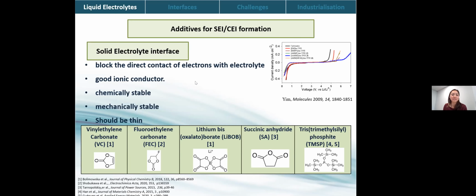It has to block the direct contact of electrons with electrolytes, and it has to be a good ionic conductor that allows lithium ions to pass through. It must be chemically stable, mechanically stable, and thin, to keep the contact resistance low. Like I mentioned, when using ionic liquids, more often than not we need additives to stabilize the SEI layer. Some examples of additives: very commonly used are VC and FEC, and recently much discussed are succinic anhydride as well as trimethylsilyl phosphite, also termed TMSP.